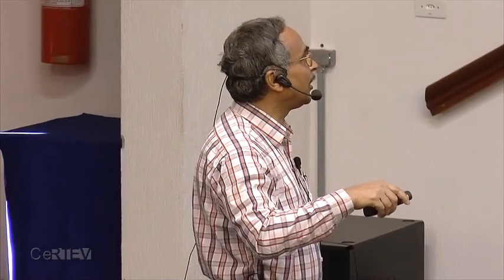If the temperature is high, then it is shown that the hopping is adiabatic, and if the temperature is intermediate, then it is non-adiabatic. And you can see the fit to these equations. So this model is very suitable to describe some of the data in some glasses without taking into account the acoustic phonons. Here is the model. This is a very complicated model. It took a long time to describe the conductivity in terms of different types of energy, phonon energy, optical phonons and acoustic phonons.